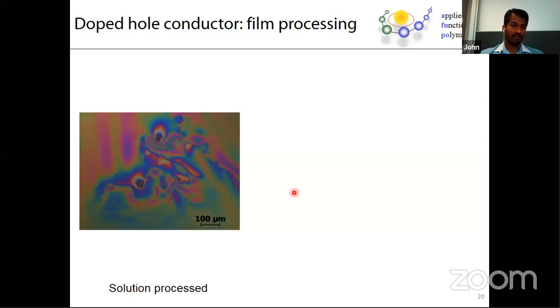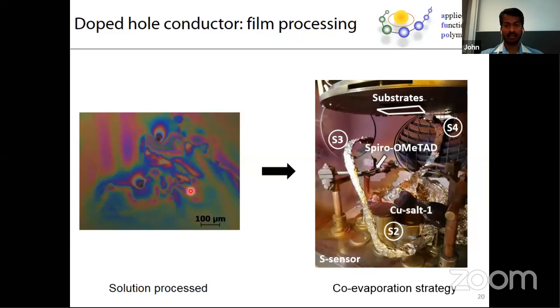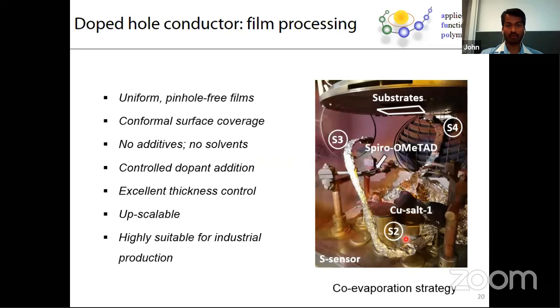So we just took spiro and copper TFSI, mixed them, and spun them on glass or ITO, and we found such strange figures in here. Because of this, we moved on to an evaporation technique, where we used different sources to evaporate these materials. And the important point is it's not just evaporation, this is called co-evaporation. You evaporate both Spiro-OMeTAD and our copper salt together at the same time with matching appropriate concentration. But we should be in control of the copper salt because we don't want to put too much copper salt in our spiro.